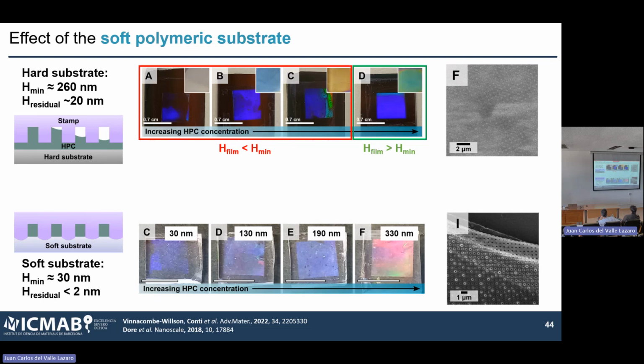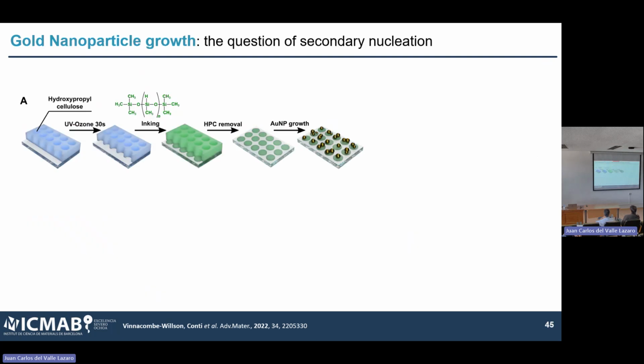So that said, we basically selected one. We didn't select the 30 nanometer one at the end because this is water soluble. So it's a good thing because I can simply wash it by dipping it in water. But it's a bad thing because if you have a humid day in the lab, you take the 30 nanometer one out and just by looking at it, it's gone. If you breathe too hard, it's gone. So we actually ended up staying on 130, 190 nanometers, which gives us a little bit of time to work.